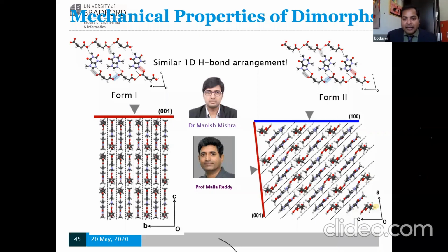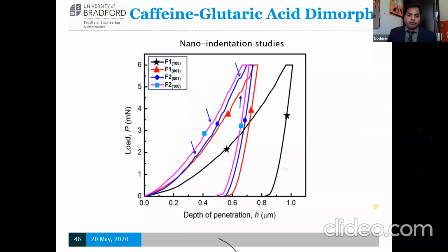the interlayer distance is quite spaced, and this is supposed to deliver some softness in the mechanical properties. Having said this, if you look at Form 2, which is a stable crystal, this is what we wanted to see. What happens? This also has slip planes. However, the arrangement of the crystalline lattice is corrugated in shape. When you apply stress from two directions, 100 or 001, it has shown that because of the alignment of crystal packing, despite having slip planes, it has shown harder crystals.